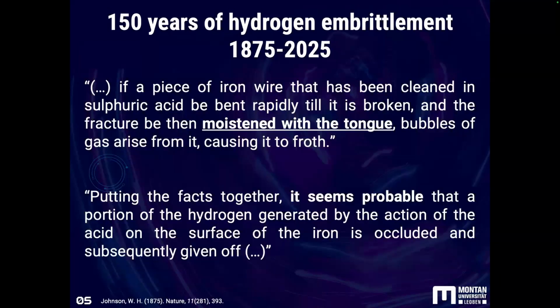And if you read the Nature paper, he says if a piece of iron wire that has been cleaned with sulfuric acid be bent rapidly until it's broken, and the fracture surface is moistened with the tongue, they used to do this, licking the fracture surface, they observed bubbles emerging from the fracture surface.